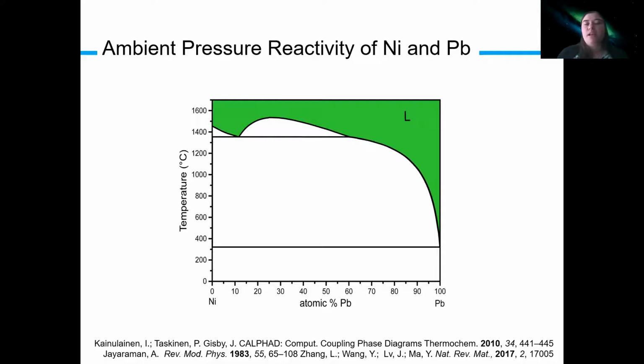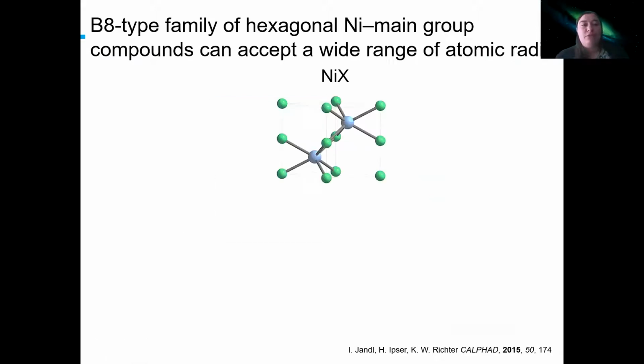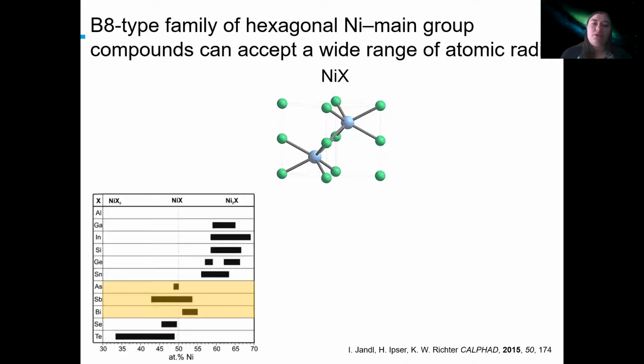And one of the reasons why nickel was so exciting to me is that there's quite a bit of reactivity with the nickel heavy main group elements. And in particular, there's this B8-type family of hexagonal nickel main group compounds. And these can accept quite a wide range of radius ratios. And this has to do with structural flexibility. So I'm going to walk through some of the structures that are formed here. So in the 1-to-1 type, it's called the nickel arsenic structure type, but it's actually formed with arsenic, antimony, and bismuth.